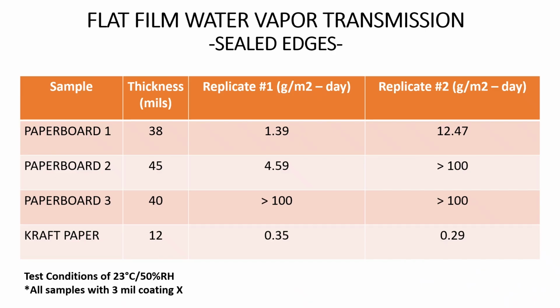once we ran all of these samples with the edges covered, the data looked very different. Now that all the moisture is actually moving through the barrier, we are seeing that these water vapor transmission rates, they went up a lot. And now all three of the paperboard structures are a lot higher and have a lot less barrier than we thought at first, because they were having that edge issue there.